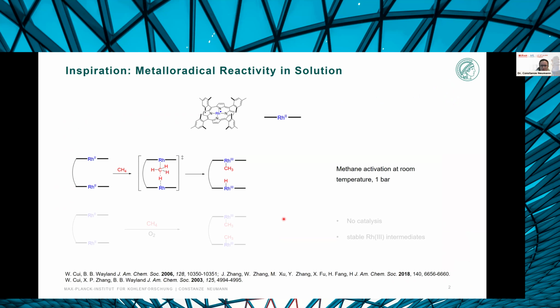And one thing that we found very inspiring was the reactivity of rhodium-2 metalloporphyrins, because there are some individual reaction steps that are extremely powerful that rhodium-2 metalloradicals can carry out, such as the activation of methane at room temperature, where there's only 1 bar of methane present. But then, despite a significant amount of work, there hasn't been any catalysis developed based on these individual steps, not even a stoichiometric transformation, because if an oxidant is added along with the methane, you don't actually get any oxidized products, but instead you get these rhodium-3 carbon-bound intermediates that are thermally very stable and obstruct catalytic turnover.